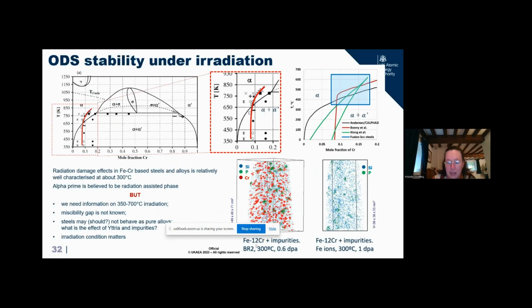Whereas if we actually go to something like the BR2 reactor overseas, which is a neutron reactor, at the same temperature and for virtually the same degree of damage, and for an identical composition, we can see the chrome segregating out in what we call the alpha prime phase.